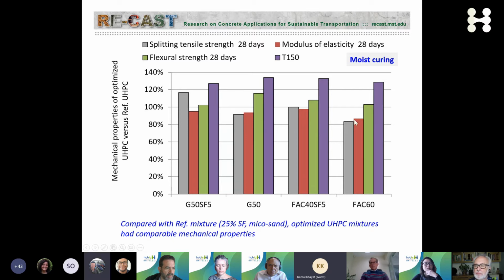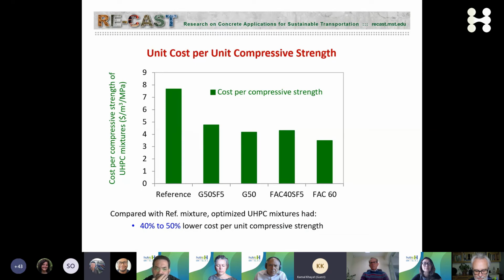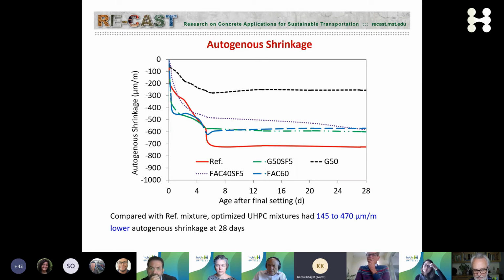We could see some reduction of strengths. Unit cost is very important. This afternoon, I have to do a unit cost for our DOT because we're doing a bridge deck using UHPC next summer. But you can see, compared to reference concrete that costs about $8 per cubic meter per MPa, the non-proprietary mixtures can be 40 to 50% less, which is a very big advantage for market penetration.